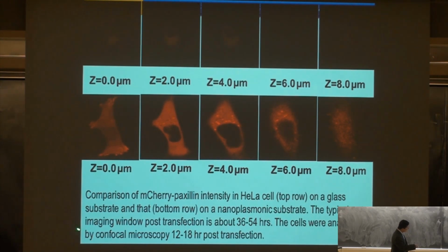In their typical case, they do imaging 36 or 54 hours after transfection, because before that they cannot see very reliable signals: the number of molecules is too low, and they don't have the sensitivity to see them. But in this study, when we culture the cells on nanostructures and then do transfection, we start doing this RFP imaging only 12 hours after transfection. So this is a very huge improvement over the status quo. You can see clearly the top row is the cell imaging on the glass slide or petri dish, which is their conventional way, and the bottom row is the imaging on our nanostructures.